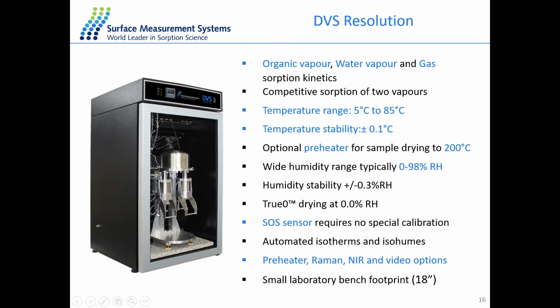And under the sample chamber here, we also have an option to put a preheater that allows you to precondition the sample up to 200 degrees before the experiment in situ, just to remove any moisture you don't want. And we also have the ability to install a Raman or IR spectroscopy at the top of the chamber here, and also a camera at the bottom here that allows you to take sample images as well as Raman spectra at the end of each humidity stage and get a complete understanding about the solid characterization.